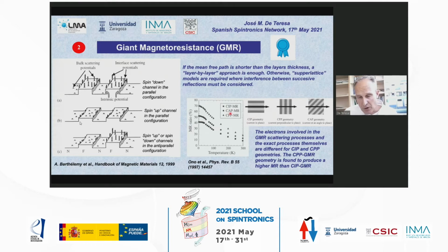First, you have to take into account that it's not the same to have a current in plane geometry, in which the current goes mostly through the layers of the stack, compared to current perpendicular to plane geometry. In this case, most of the time the current is crossing the interfaces between the different layers. And you can also have current forming an angle with the stack. The current perpendicular to plane geometry always gives higher magnetoresistance ratios compared to current in plane.